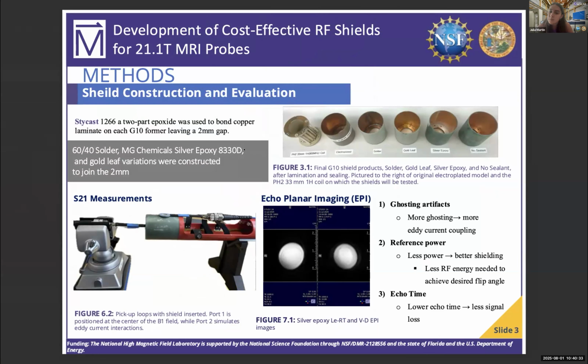In order to effectively prevent eddy currents from coupling into the circuit, each laminate must form an electrically continuous loop, which is why I developed different prototypes using 6040 solder, silver epoxy, and gold leaf as variations to join the 2 mm gap. In addition, I created a fourth variant that eliminated the 2 mm gap and pushed the starts and ends of the laminate flush with each other.